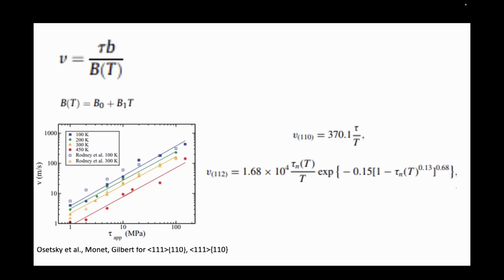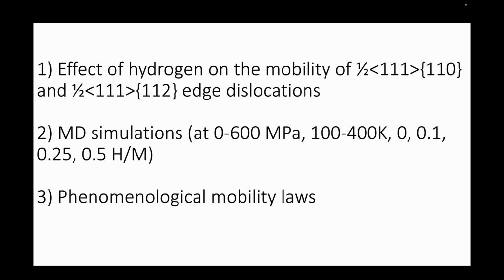It can be activated at really low stresses, maybe 5 megapascal, 10 megapascal. Since it is not thermally activated motion and it's only phonon drag, the speed of edge dislocation is inversely proportional to the temperature. And here is the mobility law of 110 and 112 in alpha iron. So the motivation of our study is just to find the effect of hydrogen on these mobility laws. We performed several simulations at different stress levels, different temperatures, and different hydrogen concentrations. And lastly, we came up with several phenomenological mobility laws for edge dislocations.